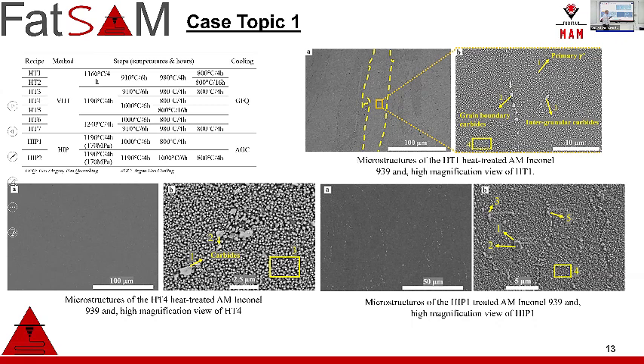So the observations were, yes, we have much more dense structures. In some of the cases, especially HT1, direct vacuum heat treatment, we don't have too much recrystallization. Melt contours are still in the microstructure. There are certain intergranular carbides, but we have a certain amount, which is expected in 939, more than 65% gamma prime precipitation. It's good. When we look at the other microstructures, HT4, when we increase the solution heat treatment and decrease the second aging, that's an issue because we couldn't dissolve all the carbides like in HT1, but we don't have too much, as you can see, melt pool or melt pad boundaries. We homogenize the samples, solutionize the eutectic regions. We have a certain amount of carbide problems, but we have well seen and coarse gamma prime precipitates.